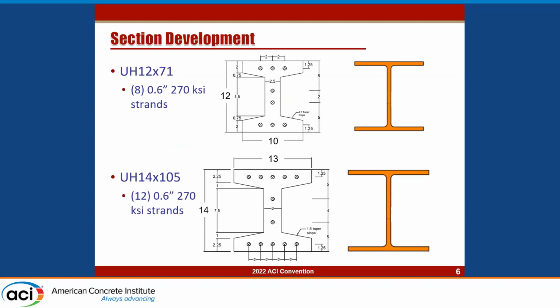So these are the sections we came up with. First, we have the UH 12x71, which has eight 0.6-inch strands, and overall the dimensions are 10 inches wide by 12 inches deep. And then we have the UH 14x105, which is overall 13 inches wide by 14 inches deep. One important note to make is that we did not provide any additional shear reinforcement in these sections. So this is what we're getting from these.